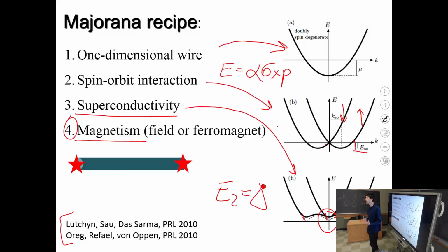And normally this is the end of the story. So if you just put a standard superconductor like aluminum in a magnetic field and make the Zeeman energy equal to the superconducting gap, superconductivity is destroyed. This is called the Pauli limit. There are other ways to destroy superconductivity, which actually normally kick in before this one, but this one is the ultimate. This is the complete finish of all superconducting things.